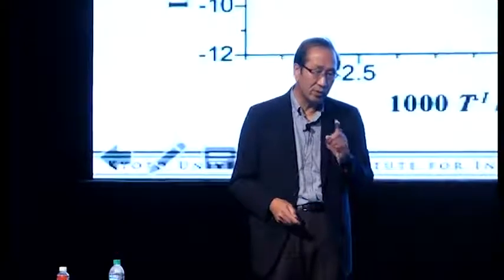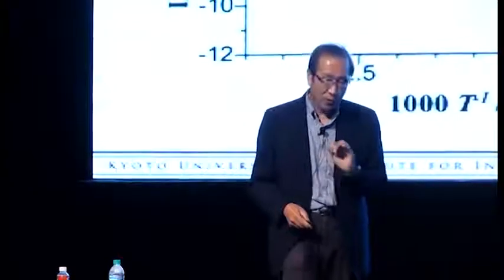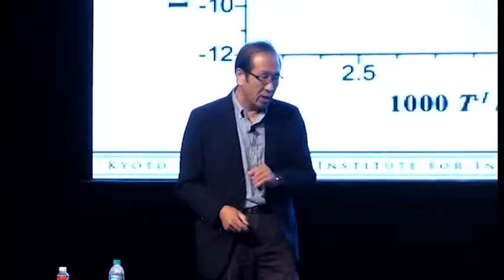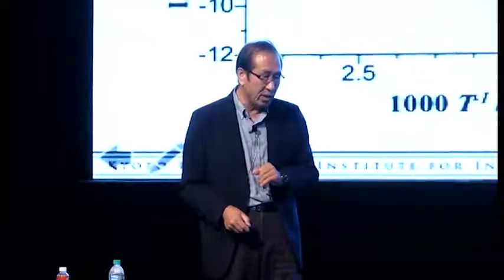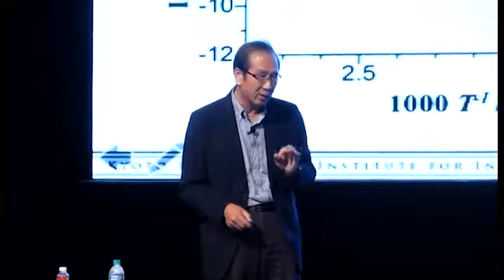So MOF and PCP have very, very interesting properties because of local dynamics. And of course, we can get the melting phase and also the glassy state phase. This is the glassy state and also the crystalline state. And we can make thin film. That's very important for the fuel cell. And the conductivity increases, in particular, in the glassy state.